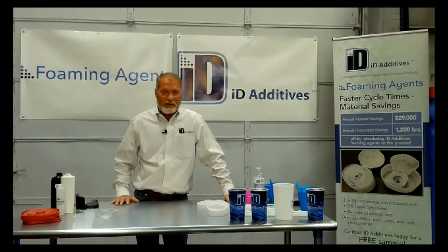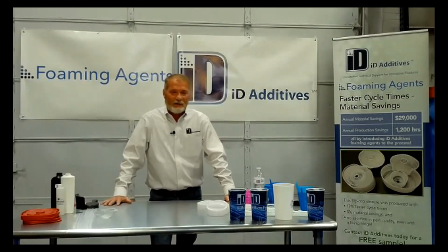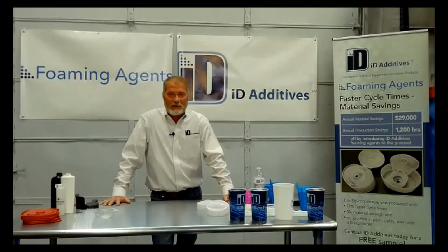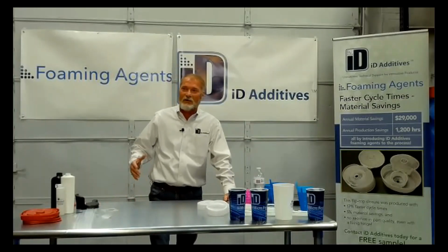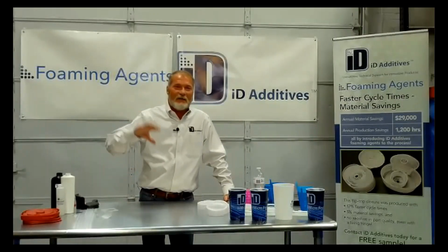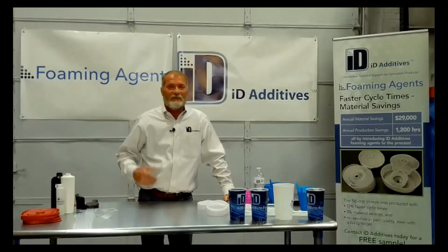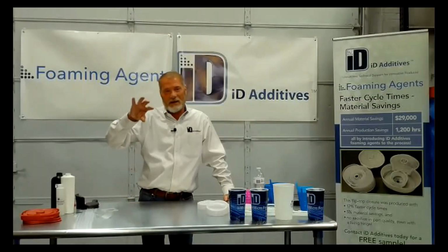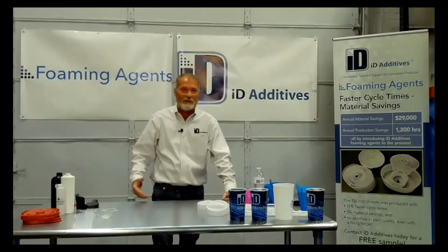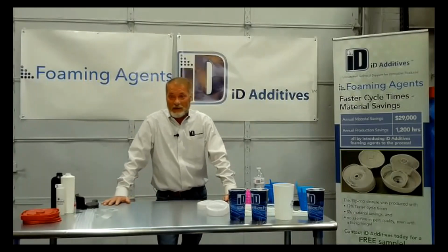So when you're running a pallet with nitrogen, always add chemical because it's going to make that pallet much stronger. The structural integrity is going to go way up. I don't know if you've ever seen a pallet where you bump it with a forklift and it breaks a corner off and there's a big hole in it. Well, that's too much nitrogen. And the reason they add all that nitrogen is they're trying to bring down the weight. But adding foam will take up where that nitrogen was. You bring the nitrogen down to where you can run faster cycles. You can improve the structural integrity and even pull more weight out of the part, at a faster cycle, that is.